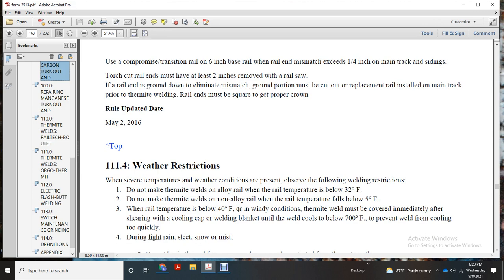Weather restriction: when adverse temperature or weather conditions are present, observe the following welding restrictions: do not make thermite welds on alloy rail when the rail temperature is below 32 degrees Fahrenheit, and do not make thermite welds on non-alloy rail when the rail temperature falls below 5 degrees. When rail temperature is below 40 degrees in windy conditions, the thermite weld must be covered immediately after shearing with a cooling cap or welding blanket until the weld cools below 700 degrees.